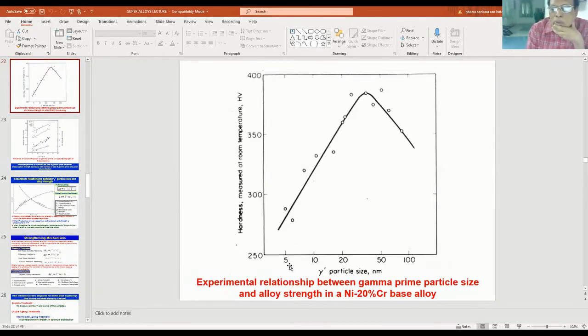See that gamma prime particle size also plays a very, very important role. Not only the shape, the size also plays a very important role. You see, this is the hardness plotted against the particle size, gamma prime size. On increasing the gamma prime particle size, strength is increasing. You look at this in the nickel 20% chromium superalloy, but after a certain size, it falls down. So when the gamma prime size is small, certain types of mechanisms are operating for contributing strength. And if you have the coarse gamma prime, strength falls down. The size here, for example, is around 40 to 50 nanometers that has been shown.